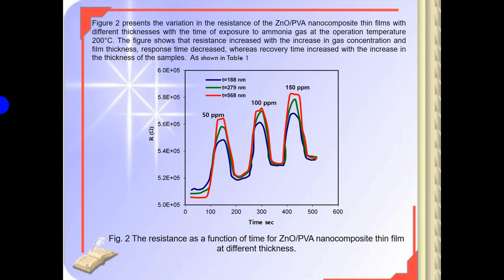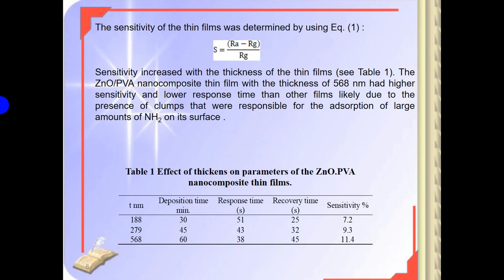Figure 2 presents the variation of the resistance of the ZnO-PVA nanocomposite thin film with different thicknesses with the time of exposure to ammonia gas at an operating temperature of 200 centigrade. The figure shows the resistance increases with the increased gas concentration and the film thickness. Response time decreases, whereas recovery time increases with the increase in the thickness of the sample, as shown in Table 1. The sensitivity of the thin film was determined using equation 1. Sensitivity increased with increased thickness of the thin film, as seen in Table 1.